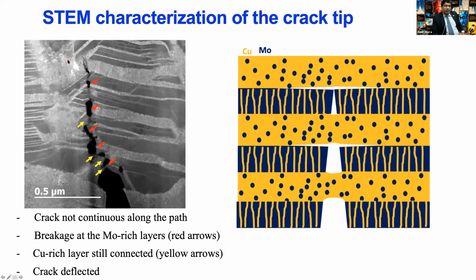Now, from that in situ test, because the sample was intact, we were able to section and do a FIB lift out and observe the crack tip inside a TEM. So this is now a STEM image of the crack tip. And you can see that hierarchical structure, the matrix where you see very fine scale striations, the darker regions are copper rich, which have those moly precipitates that almost look linear, but that's just a row of moly precipitates. And you can see all kinds of toughening mechanisms. There is crack bridging, there is deflection along the copper moly interface, and there's significant plasticity and crack meandering.